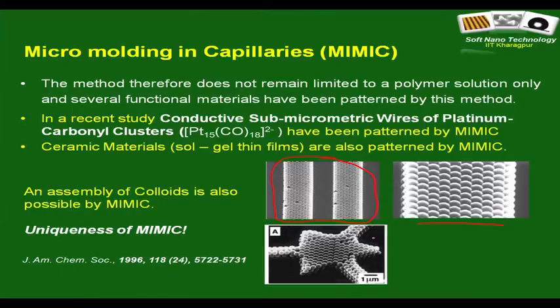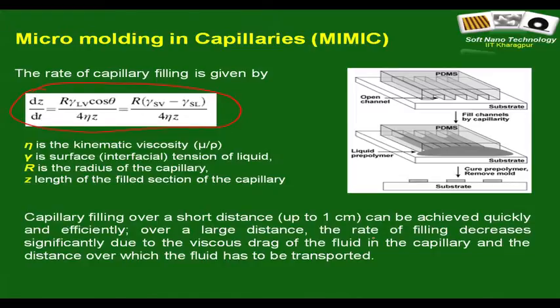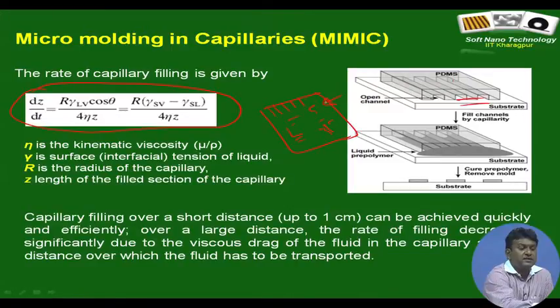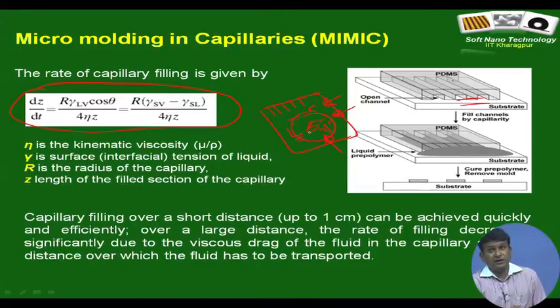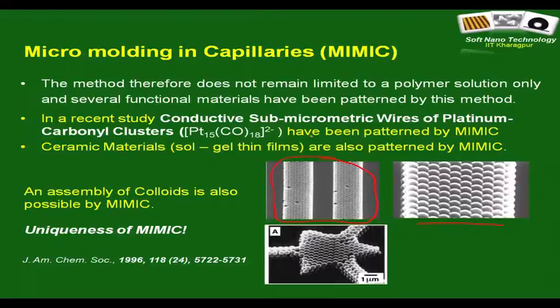One major limitation of MIMIC, of course, is that every area below your stamp has to be reached by the liquid. So, we have been talking only about gratings like this, which is fine, but for any complex geometry, the entire pattern has to be connected to the sides, so that the solution can reach that area. That is one of the limitations. Particularly, you now realize that MIMIC does not work well for patterning over large area, because the capillary driving force drops too drastically.